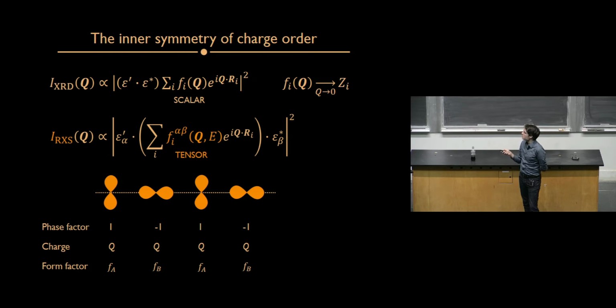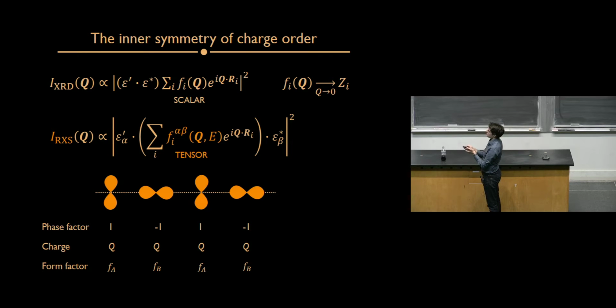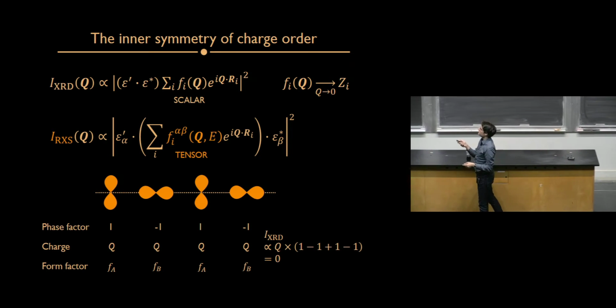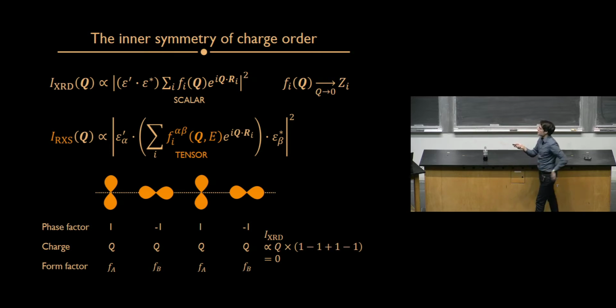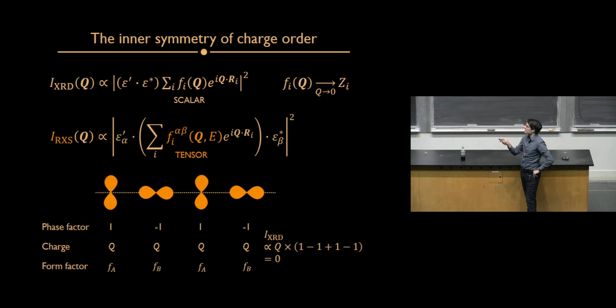So what we do now, we have to take this summation here for the case of diffraction and scattering, and what I need here is this phase factor, which is e to the iq dot r. So I have this period 2 orbital order, which means that your q is 2 pi over 2. So here is this phase factor, here is 1, here is -1, here is 1, here is -1. Okay, that's the interference factor between different atoms that give you the diffraction process. Total amount of charge here is the same, because there is 1 electron here, 1 electron here, 1 electron here, 1 electron here. But this form factor that enters only the resonant X-ray cross-section is different from this site, let's say the A site and the B site, because it reflects the orientational properties of the orbitals, not just the total amount of charge. So if I take this summation here, evaluate it for these 4 orbitals here, then I get 1 minus 1 plus 1 minus 1, because these are the phase factors that enter here, right?